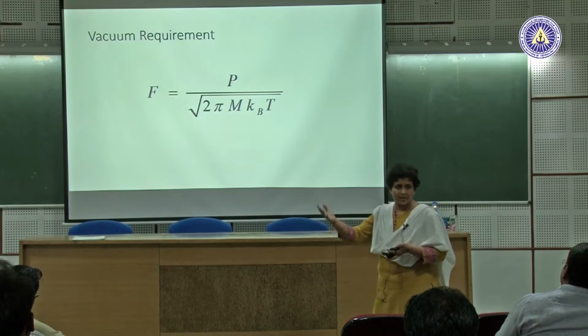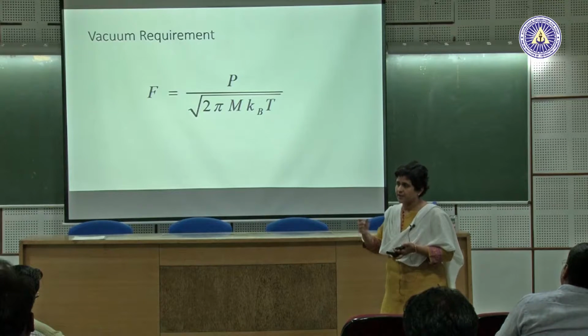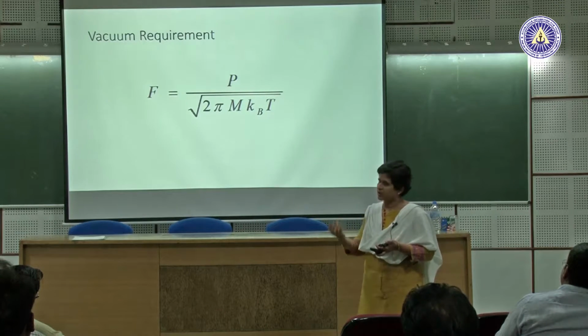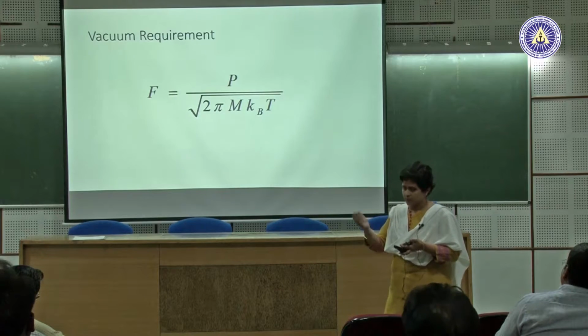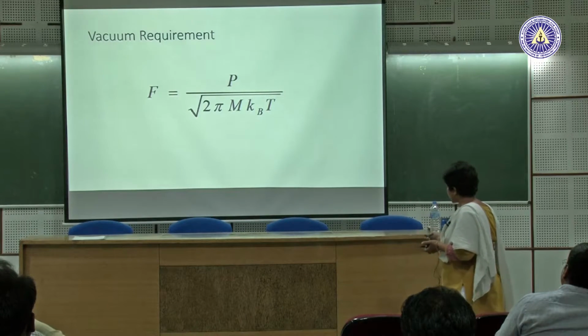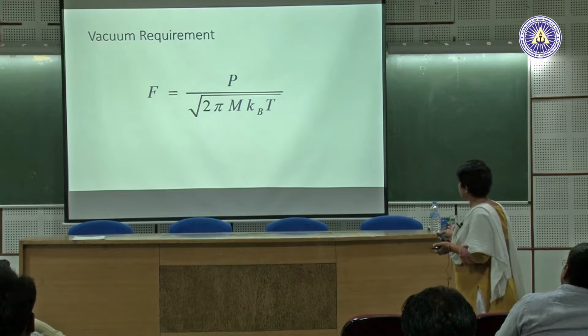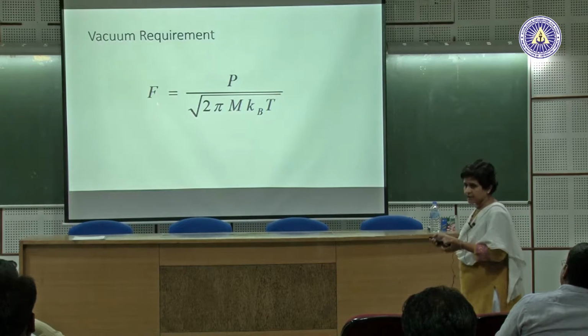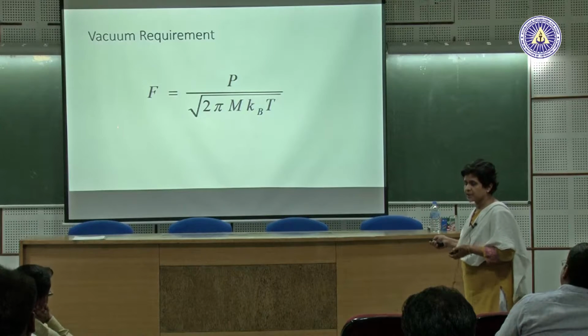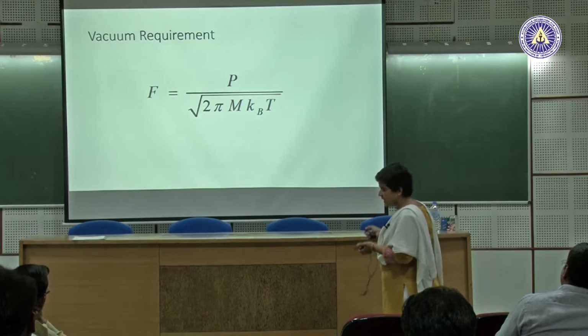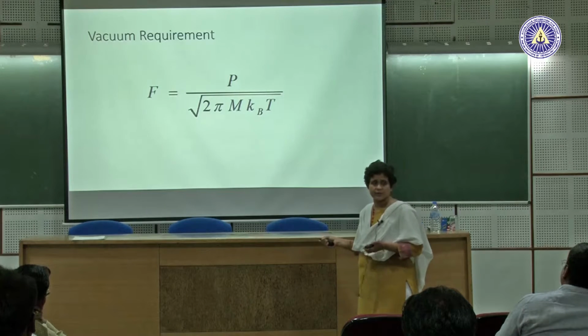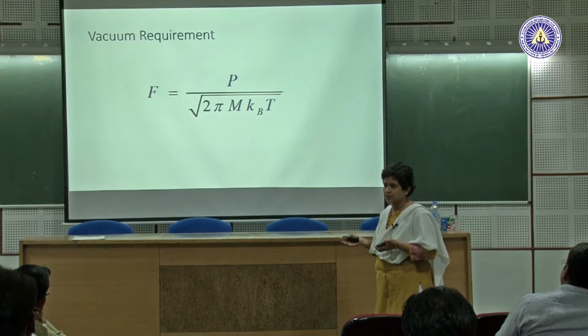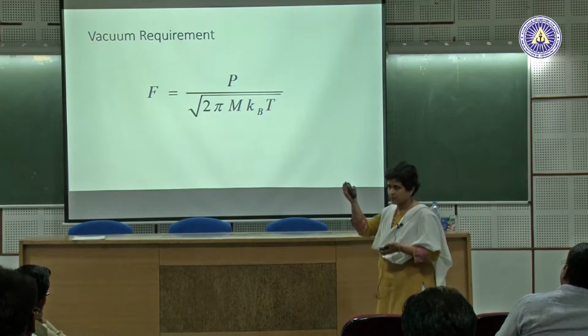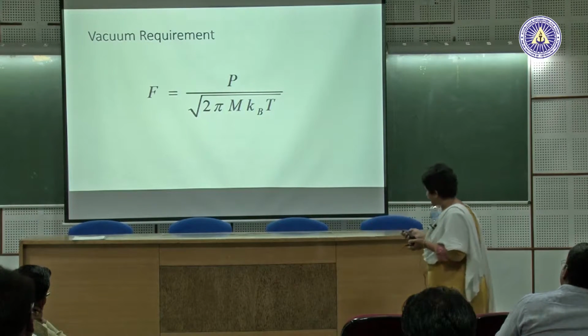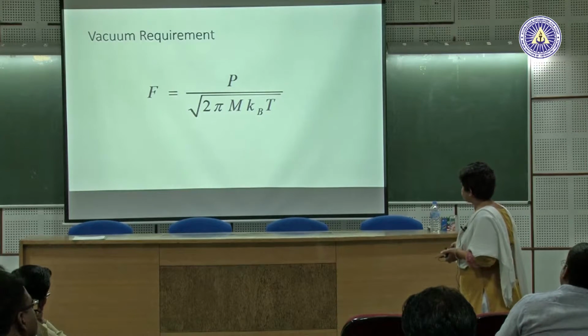The more high temperature metals you take, the more difficult it becomes to evaporate, and then you may have to go to E-beam deposition, because you can't just give it enough heat to get to a temperature where evaporation is possible. So one can calculate the flux of atoms coming to the substrate per centimeter square per second, and from there one can get a deposition rate. This is the kind of science people do when they are depositing something. They try to see, if I change temperature, how much my deposition rate is changing for the film. These are the manufacturing parameters that you can control here.